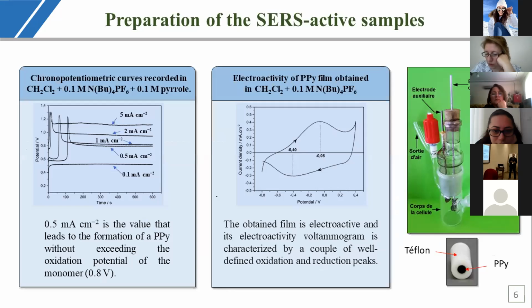The second step is the electrodeposition of polypyrrole on the previously activated silver electrode using the galvanostatic mode. The preparation of the polymer was achieved in the well-known three-electrode system with a solution of dichloromethane. By applying different current densities, we found that a value of 0.5 is the best one that led to the formation of homogeneous and very adherent polypyrrole without exceeding the oxidation potential of the monomer, which is in this case 0.8 volt. The obtained film is electroactive, and its electroactivity is characterized by a couple of well-defined redox peaks.